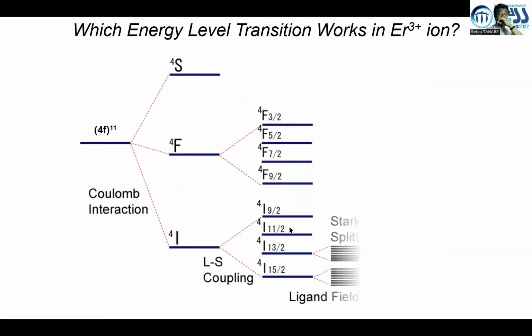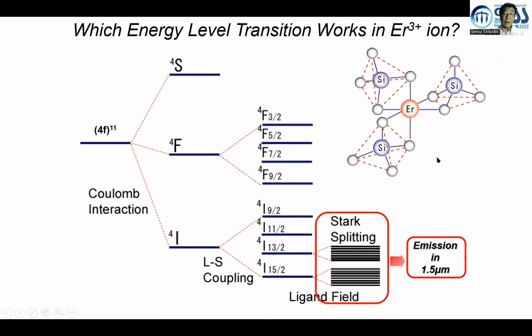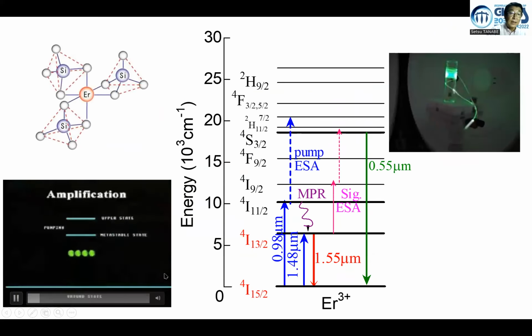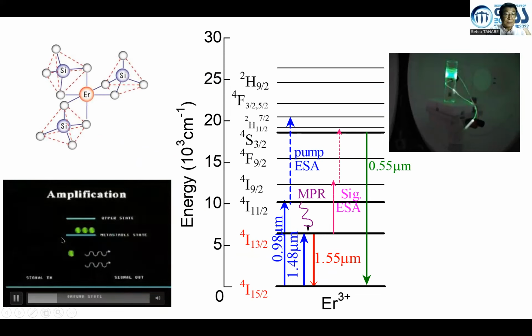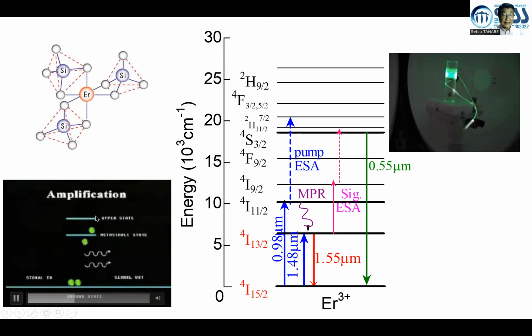So this is the Coulomb interaction of erbium levels, quartet I, quartet F, and quartet S. Important are the ground state, 4I15/2, and the first excited 4I13/2 level, which has Stark splitting into 8 or 7 components. That is utilized for the emission in the 1.5 micron region. It is utilized by exciting to the second excited state, which is the 4I11/2 level,